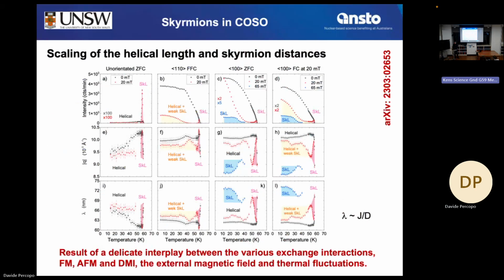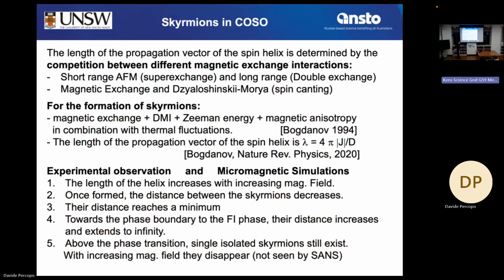Okay, some core results, and here some theoretical explanation of this effect. The key line is the formation of skyrmions. We have magnetic exchange interaction plus the Dzyaloshinskii-Moriya interaction plus Zeeman energy coming from the external applied magnetic field plus magnetic anisotropy from every single copper ion in combination with thermal fluctuations. So 5 in total.